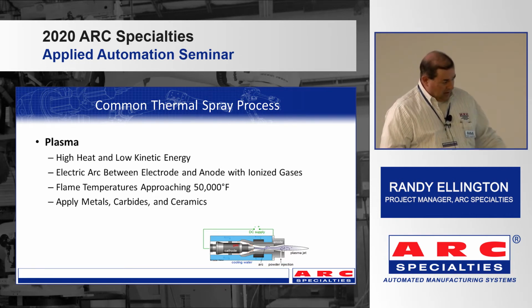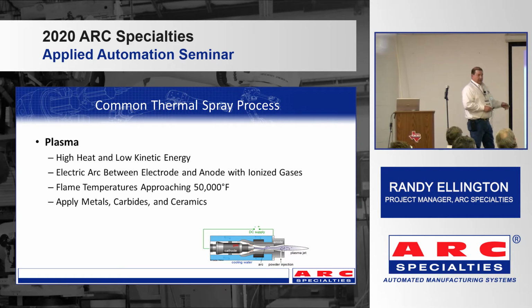And I guess the big difference in this and what most people, when you think of plasma, you think of plasma cutting or plasma welding. In those processes, you're actually transferring the arc to your substrate. In this one, the arc is actually staying with the torch, not transferring to the part. We're just creating an arc using ionizing gases to push that arc out of the torch a little bit to where we can inject our powder and heat it and propel it at the substrate.